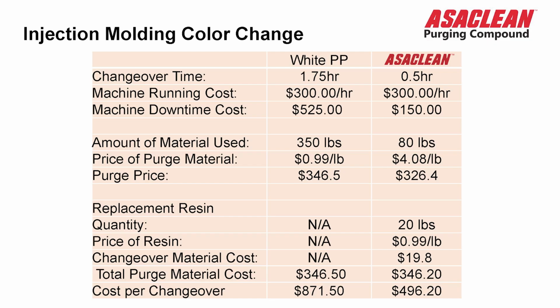We take a look at the machine running cost and current downtime cost, and we come up with a bottom line number where this color change is costing this injection molder approximately, in this particular case, $871.50. After we use the Asaclean purge, we reduce the time from an hour and 45 minutes to 30 minutes.